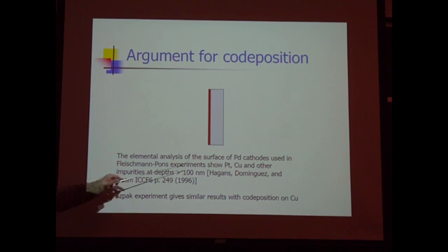An elemental surface analysis of the surface of the palladium cathodes in the Fleischmann and Pons experiment was carried out many times. Here's one reference for it. But platinum, copper, and other impurities are seen at depths greater than 1,000 angstroms. You might say, well, why should that happen? And the reason is that platinum, as a noble metal at the anode, isn't supposed to be attacked because it's noble, but it does get attacked some.